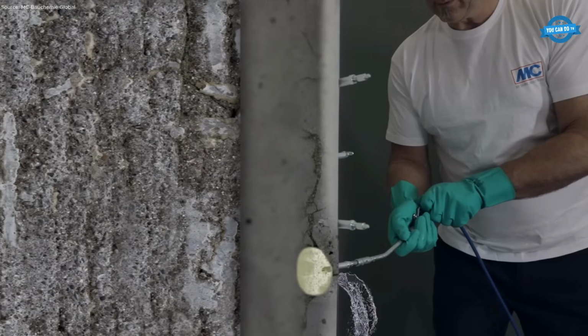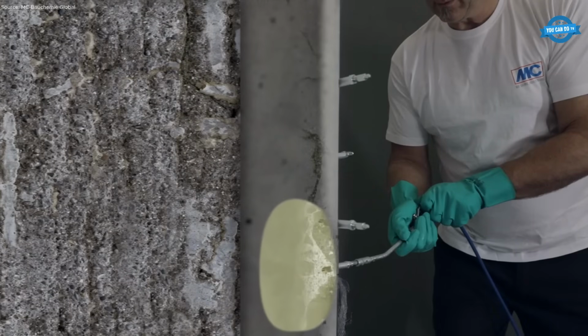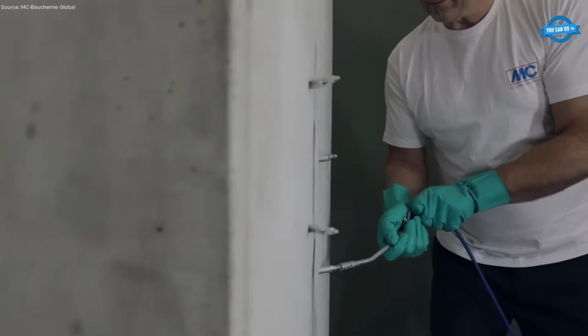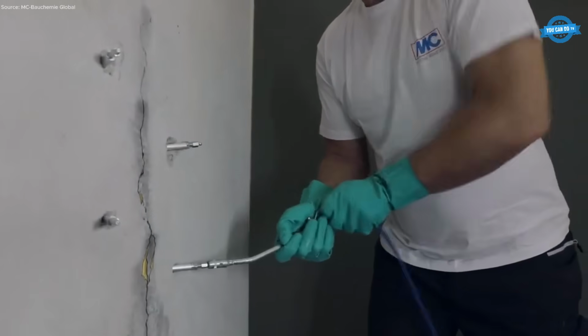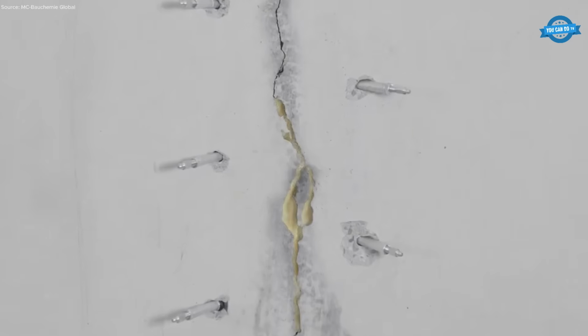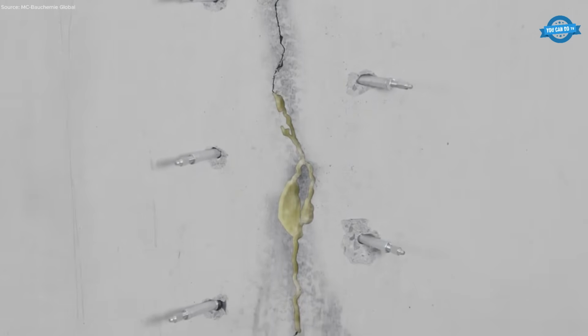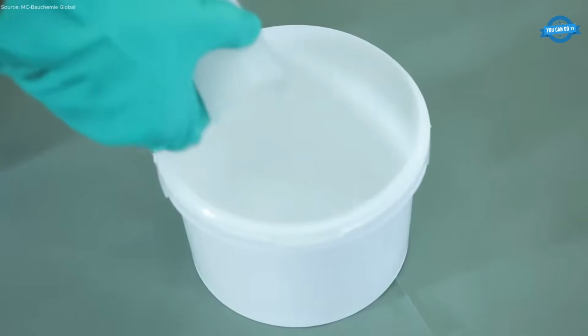This ready-to-use resin requires no mixing and features unlimited pot life, allowing for flexible, time-efficient application. Simply drill into the crack, insert the injection packer, and inject the resin. The material reacts immediately with water, forming a dense closed-cell foam that blocks further ingress.